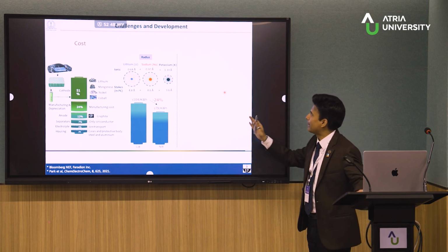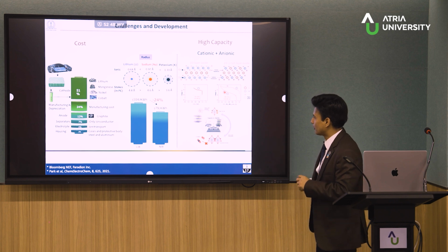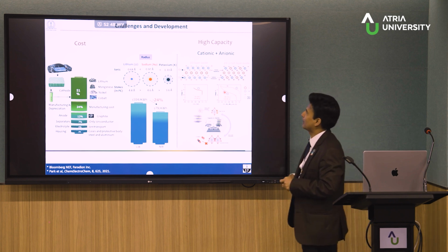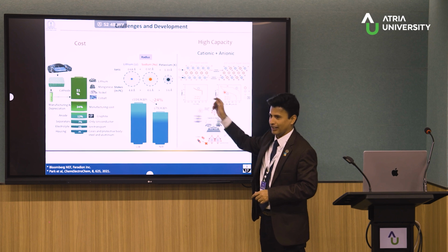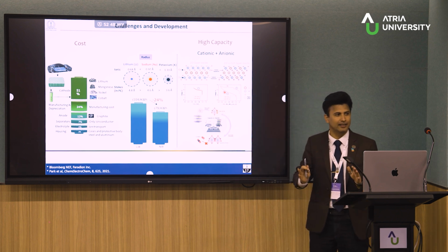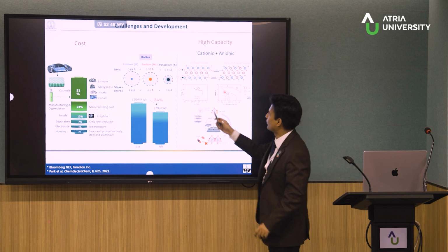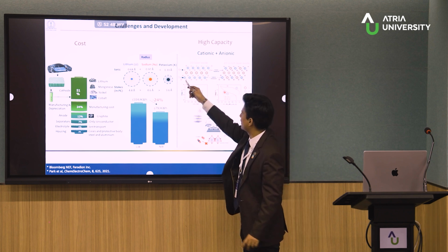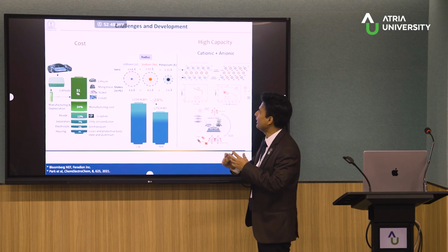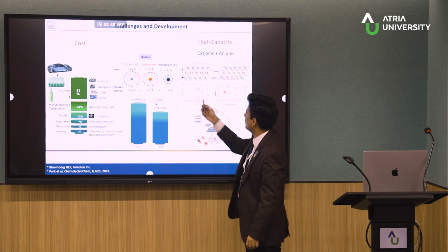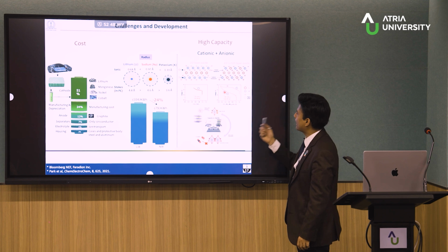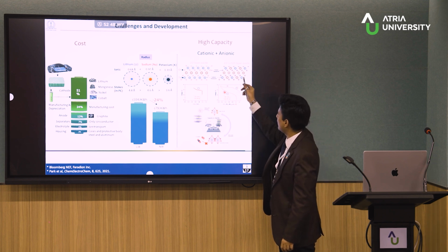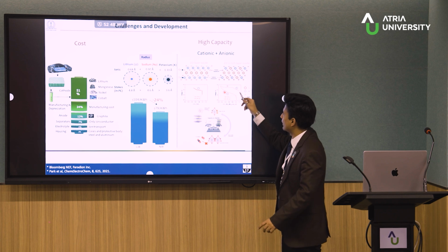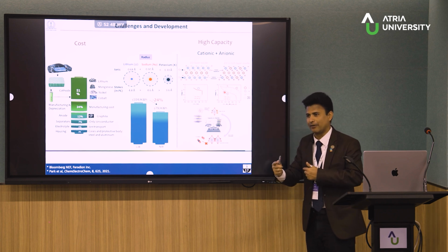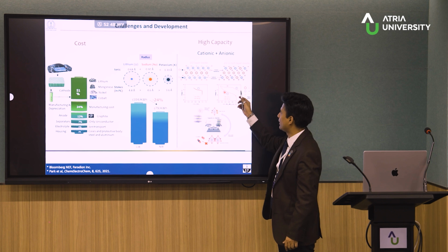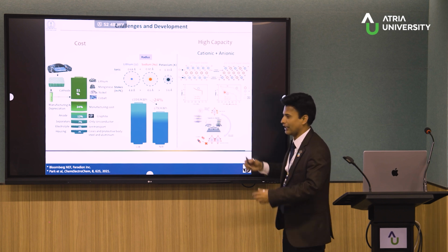Now, this is all about the material perspective and challenge, and also just from a fundamental perspective, everybody talks about cationic redox. This is the classical thinking: we have a layered structure where the transition metal changes the redox state without changing position, and that leads to the capacity. But now there is also a concept called anionic redox, where in addition to the cation, the oxygen, the anion, can also take part in some redox activity at high voltage. As a result, we can combine the capacity contribution from cationic as well as anionic to get in principle very, very high capacity.